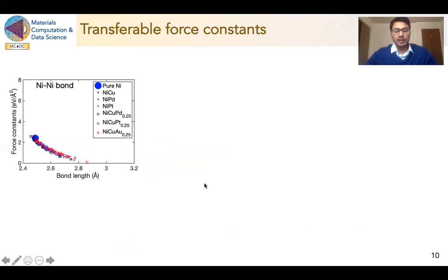So we have calculated using DFT the force constants in various alloys. In this figure, the vertical axis is the force constants and the horizontal axis is the bond length. And the force constants of the nickel-nickel bond in various systems, including pure nickel, 3 binary and 3 ternary systems, are shown in this figure. You can see that some of the nickel-nickel bonds are shrunk and some of the nickel-nickel bonds are actually strained. But the important point to note here is all the force constants follow a curve in all these alloys, which shows that the force constants are only dependent on the bond length, and they are not dependent on the chemical environment, the chemical composition of the alloy considered.